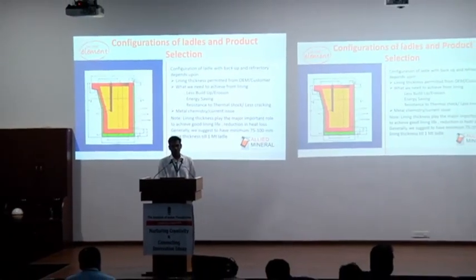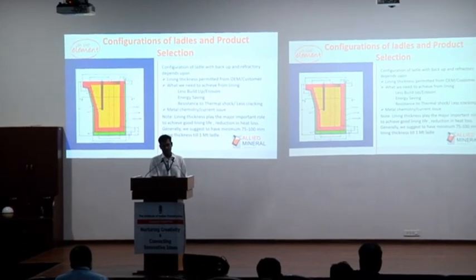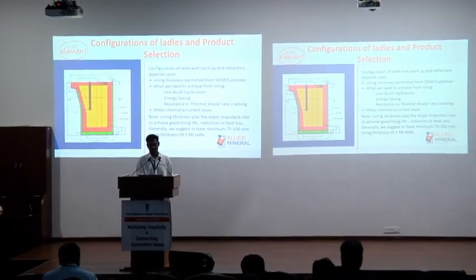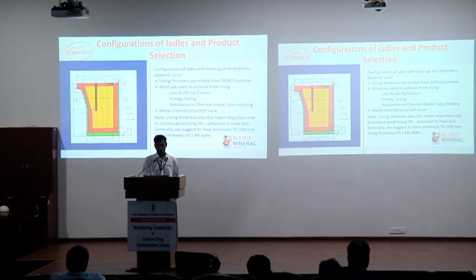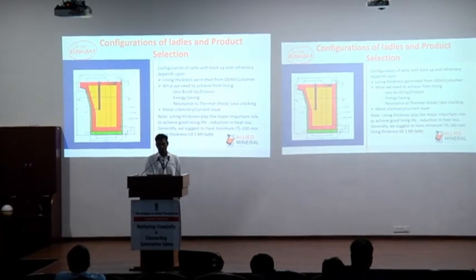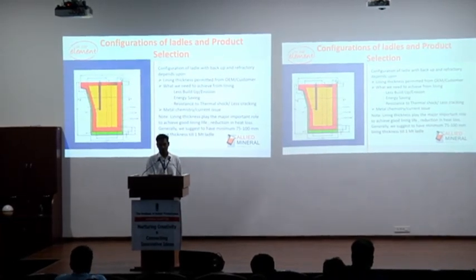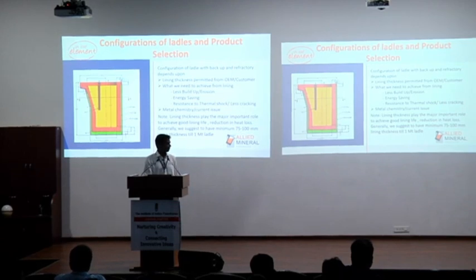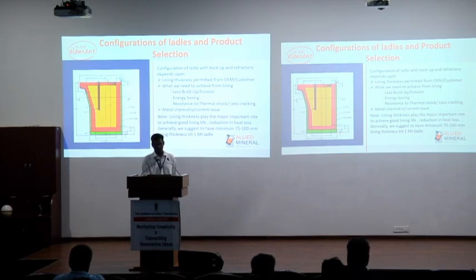So lining configuration is based on what we would like to achieve: more lining life, energy savings, less build-up, erosion, cracking and metal penetration. Based on the chemistry, we suggest a configuration. We normally recommend to our customers a lining thickness between 75 mm to 100 mm for a 1 metric ton ladle, so that we can achieve the best lining life with less heat loss, because most of the foundries in India are not practicing or not having a proper lining thickness with respect to the ladles.